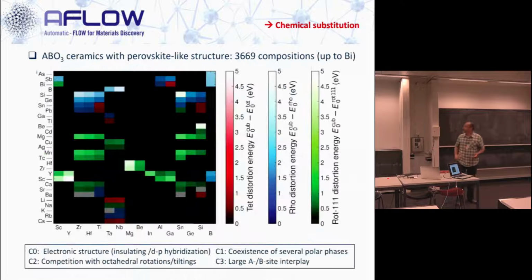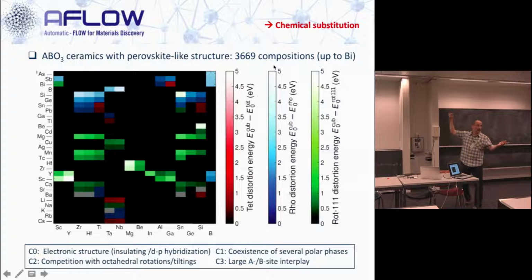Okay, so we put them in the database, and then we start processing, right? So we have our total number of calculations. We went up to bismuth. Okay, this is actually very important. You know, we could not push this through the lanthanides because we cannot, at this point, trust the pseudopotential from a high-throughput point of view for the lanthanides, for the F elements. And then we start analyzing the data.